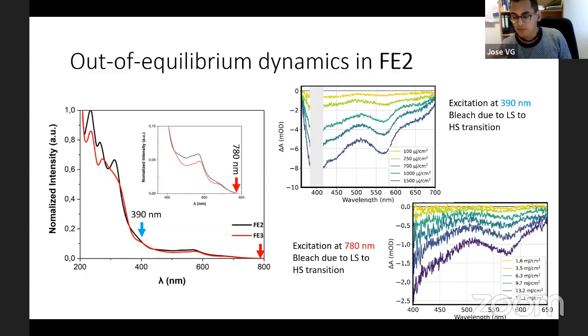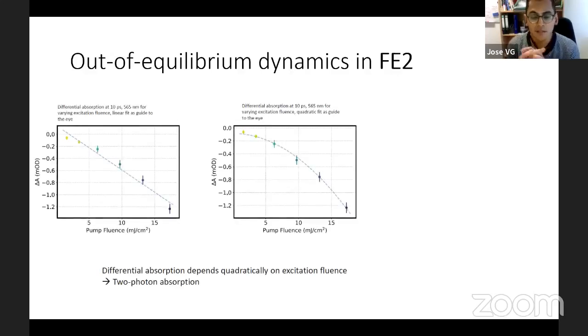So, and we observe similar bleaching at both 390 and 780. However, we have to use much higher laser excitation at 780 nanometers. What is the reason for that? Well, what we expected is that we are having a 2-photon absorption. In other words, we're having a spin crossover because of 2-photon absorption. And this seems to be the first time we observe this phenomenon in this kind of complexes. And we have registered it by both optical transient absorption and by photocrystallography.